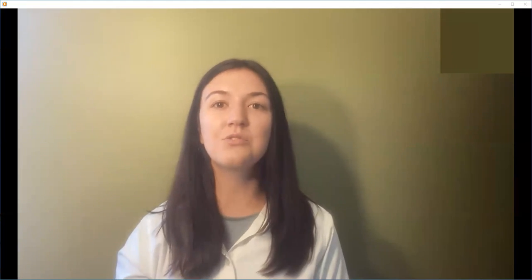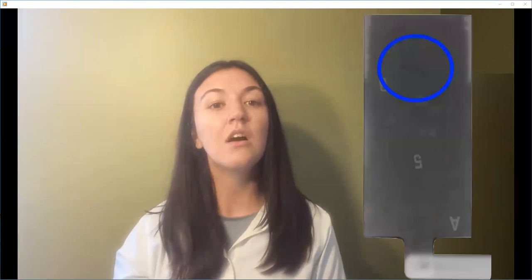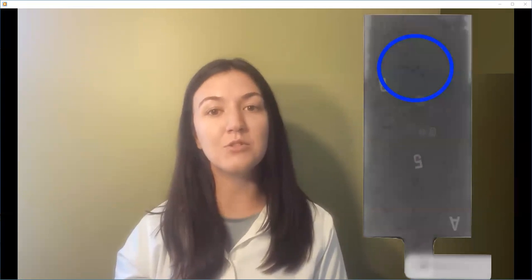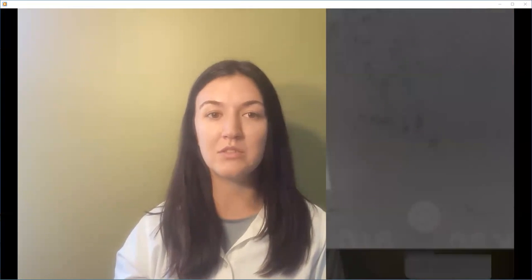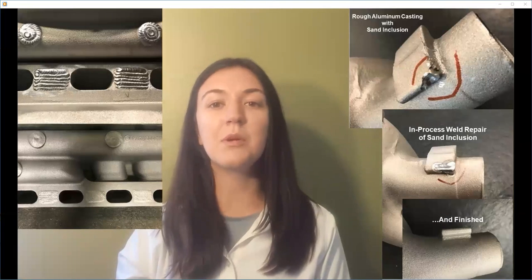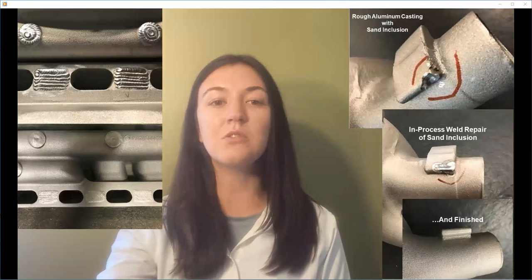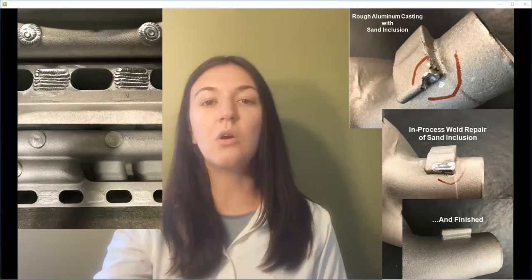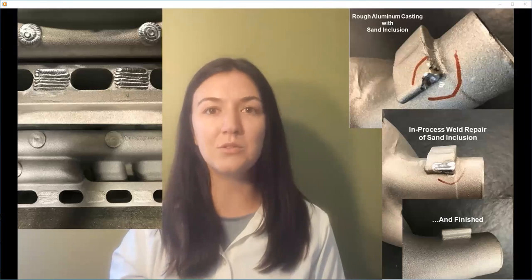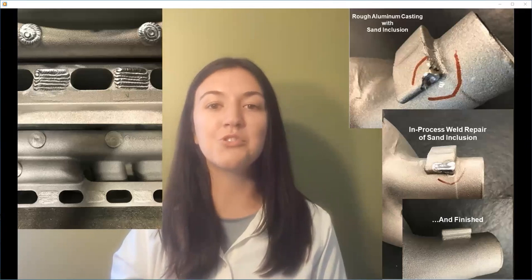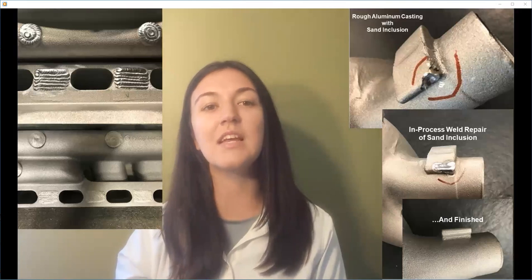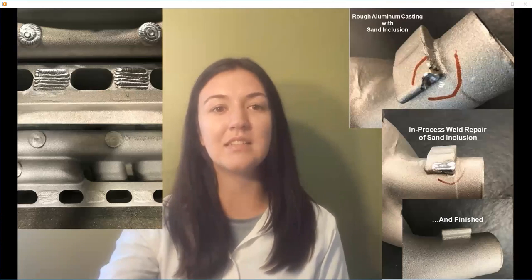Non-destructive testing is used to assure solidification integrity on casting surfaces. Freedom from cracks or hot tears is tested by magnetic particle or dye penetrant inspection, or casting internal integrity, which is specified levels of acceptable internal porosity tested by radiography. In-process weld rework is used to repair surface or internal integrity anomalies. As always, a repaired surface must include blending of the repair to assure compliance with dimensional tolerances and surface finish in that region of the casting.